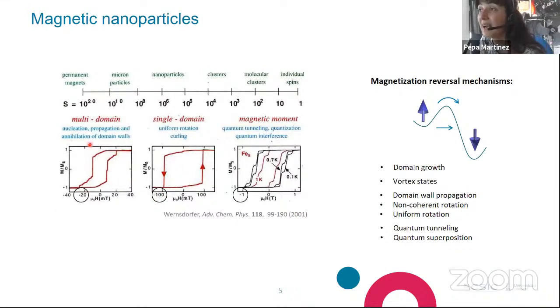For instance, large objects, where usually the formation and movement of domain walls is the main mechanism, usually exhibit these typical peaks, or typical steps, in their hysteresis curve. When we go to smaller objects, where the particle is said to be in the single domain state, so all magnetic moments are almost always collinear between them, okay? One finds these typical square shape hysteresis curves.